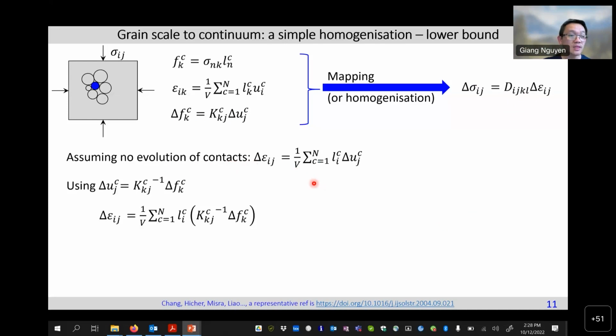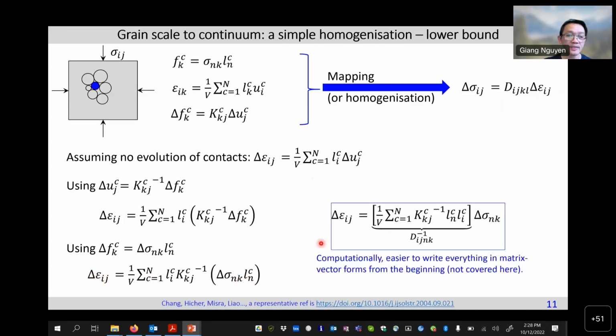If we do that, we do substitution. I skip the details here just to cover the message. In the end we get a link, as you can see here, between the macro strain and macro stress, and we can rearrange this in our preferred way. In this case, we have the compliance matrix linking the macro strain increment with the macro stress increment. I won't cover the computational aspects here, but it's usually easy to write things in matrix-vector form to get something easy for implementation later.